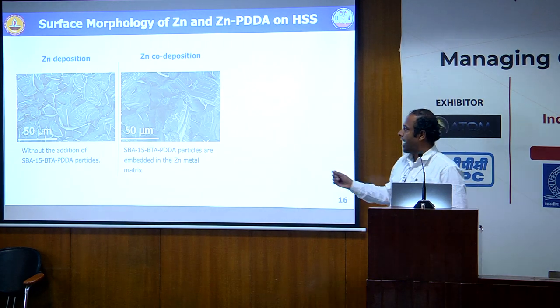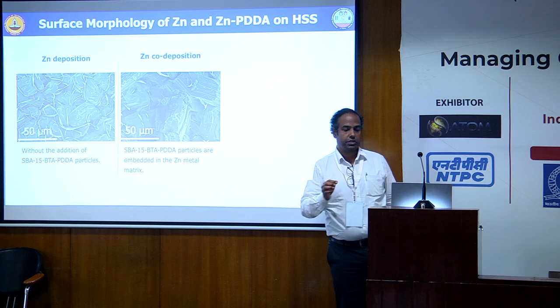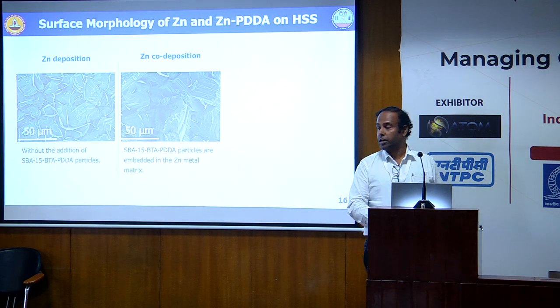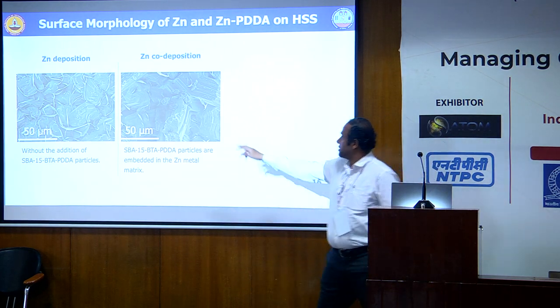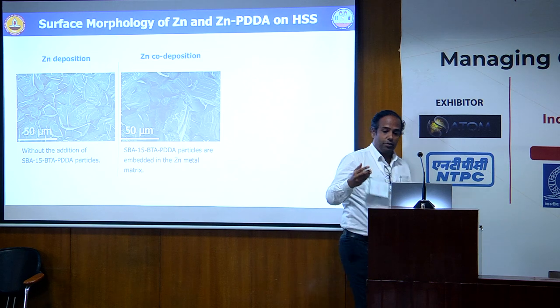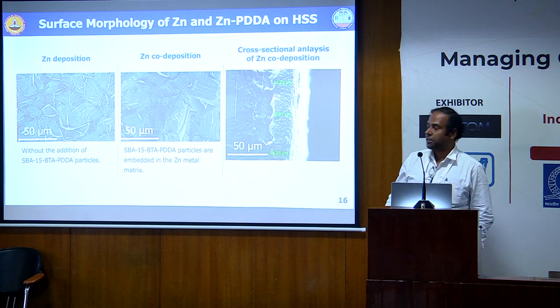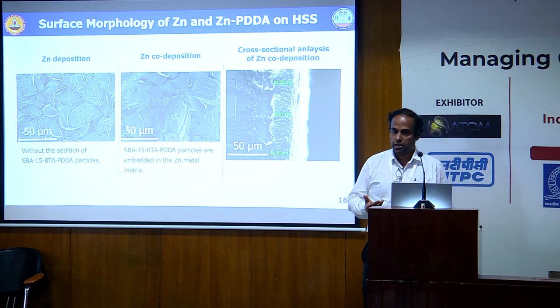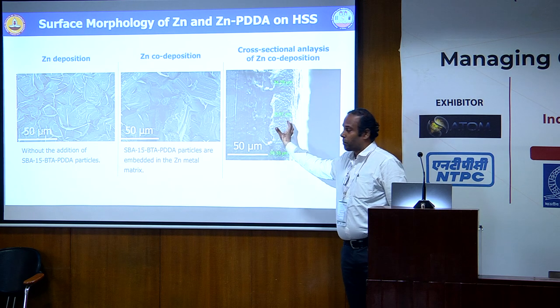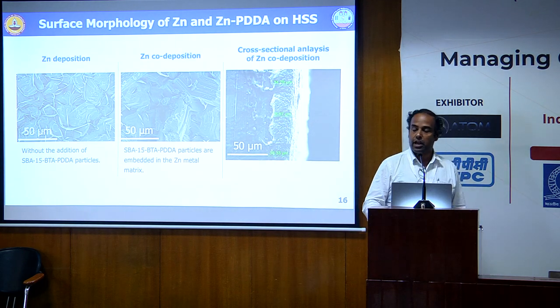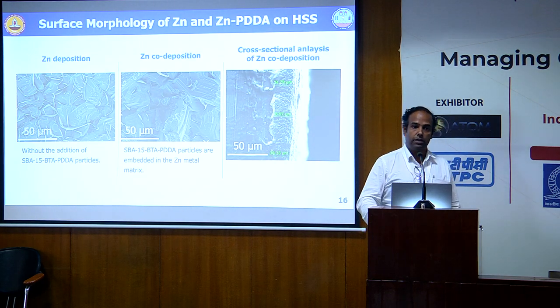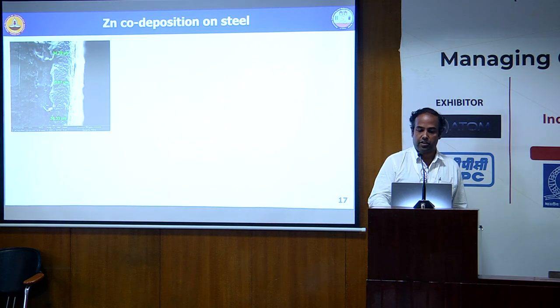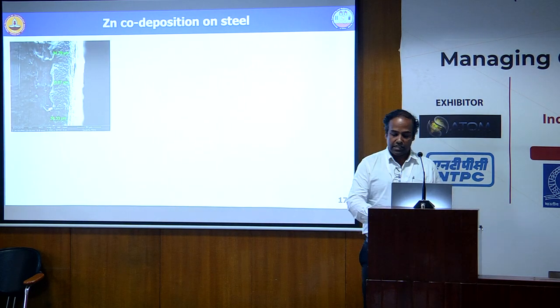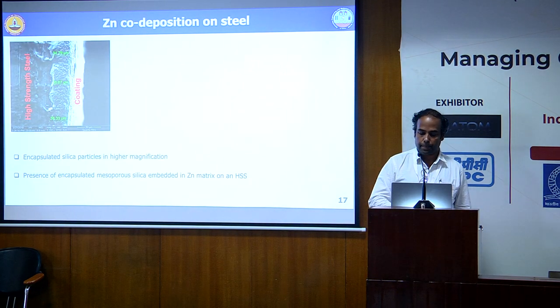And on the right, I added PDDA particles of a certain concentration. You can see it really on the surface. These are the particles which are present. If I have to say that yes, we found it in, then I need to study the cross-sectional image. So what we did, we deposited approximately 40 microns of zinc layer along with these particles. And then we look at whether the silica particles are really present in the coating.